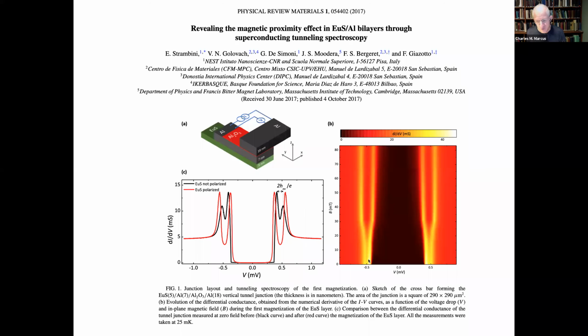It only took 30 millitesla to fully magnetize. You know, there was a saturation field of 30 millitesla. Below that, you're only left down here with a remnant field, which is large, but not as large as the saturation field. That's the first important point. And the second important point is it didn't collapse the gap. There's still a good superconducting gap in this density of states measurement.